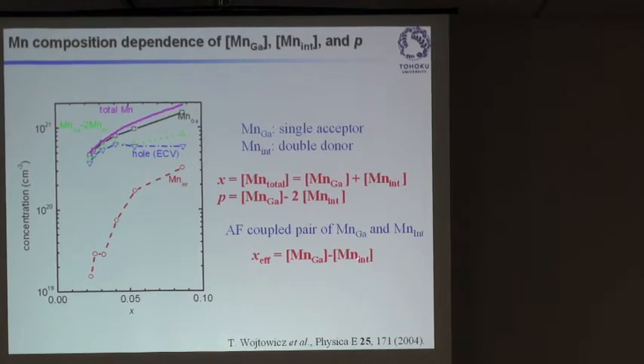In addition, there is an antiferromagnetic coupling between manganese in the gallium site and manganese interstitial. And this gives you a lower potential energy. So most of the manganese interstitial tends to form an antiferromagnetic coupling with manganese in the gallium site. And because this is antiferromagnetic coupling, by measuring magnetization, we do not see those coupled manganeses. So that means that our effective concentration is equal to manganese in the gallium site minus manganese in the interstitial site. This is the concentration that you see by doing magnetization measurements. So there's a lot of compensation in different ways going on in the system.